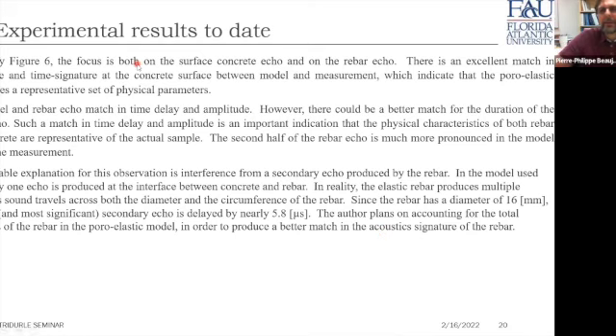Now, a few clarifications regarding the experimental results to date. To clarify figure 6, the focus is both on the surface concrete echo and on the rebar echo. There is an excellent match in amplitude and time signature at the concrete surface between model and measurement, which indicates that the Poro-Elastic model uses a representative set of physical parameters. In plain words, it means that the Poro-Elastic model I'm using is doing a pretty good job given the set of physical parameters we actually used for the concrete and for the rebar. These parameters are very, very close to what we believe to be the actual values.